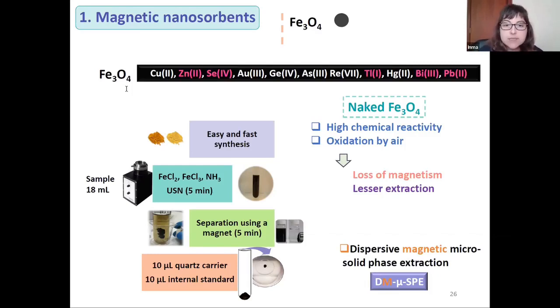Because this synthesis is very easy. In the first case, in a vial, we add the chloride salts of iron 2 and iron 3 in the presence of sample solution or standard solution, and we add ammonia. Then we have to sonicate in a cup horn sonoreactor for 5 minutes, and at the same time, you can see that the nanoparticles of magnetite were formed by coprecipitation, and also some of the elements are trapped by occlusion, and other elements can be added by surface adsorption to these magnetic nanoparticles.